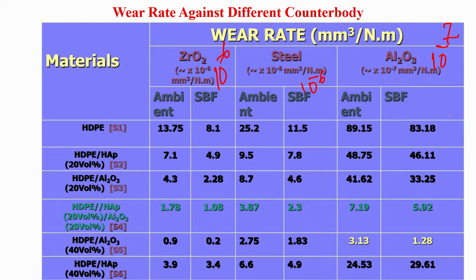So in case of alumina, there is generally a 1 order of magnitude difference. But if you look at this 10 to the power minus 7 here, 83 into 10 to the power minus 7 is nothing but 8.3 into 10 to the power minus 6. So that way this value and this value are comparable.